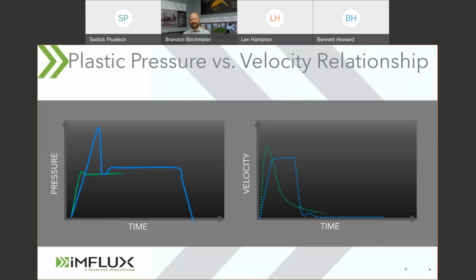iMFLUX is a very interesting velocity profile. So at constant pressure, I mentioned we fill slower, but we're not always filling slow. As you'll see comparatively here, at that lower pressure, my velocity as I'm approaching my pressure set point is actually pretty fast. We do want to still take advantage of the shear thinning properties of the polymer, but we don't believe we need to do it for the entire 90-95% of the part volume. So what happens here is we get a hyperbolic relationship in velocity until we hit that pressure set point, and then we begin a parabolic slowdown in the velocity.